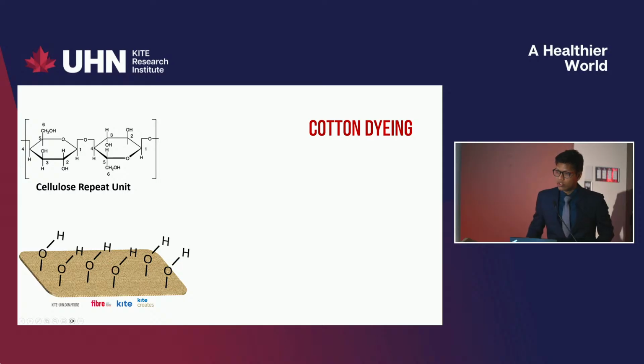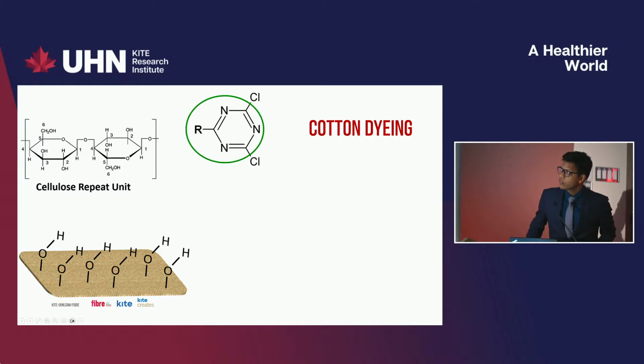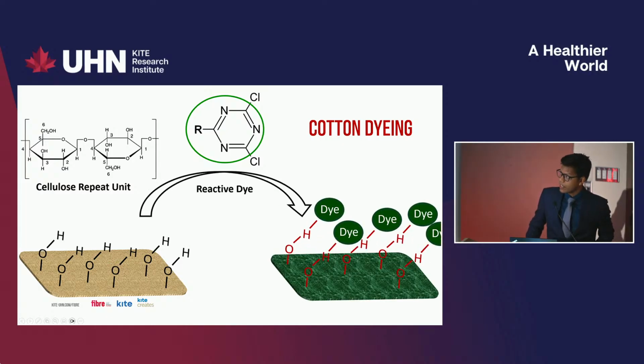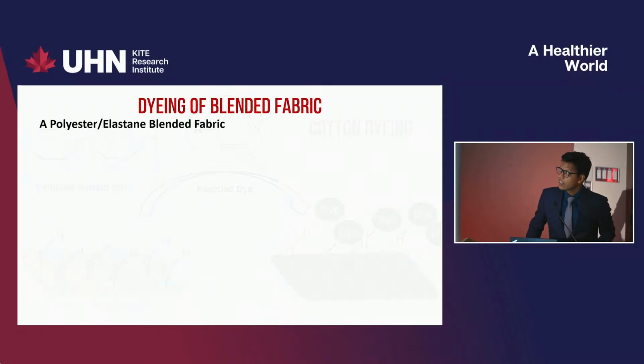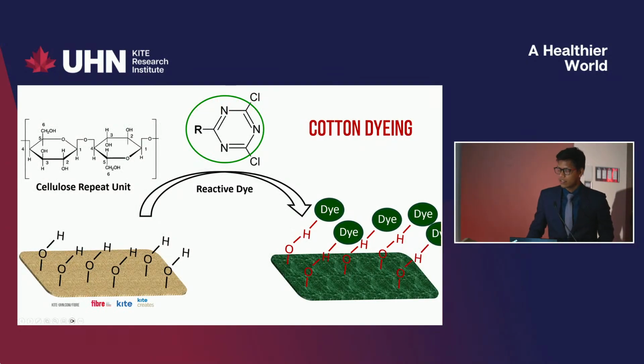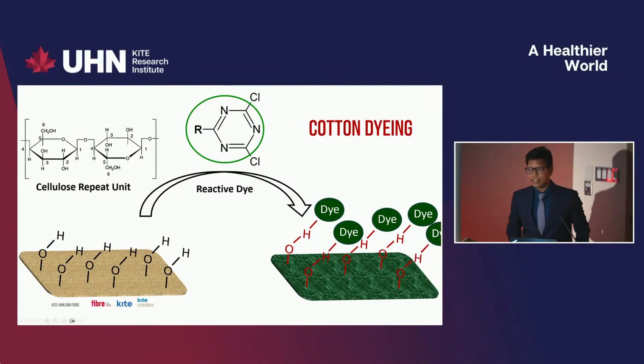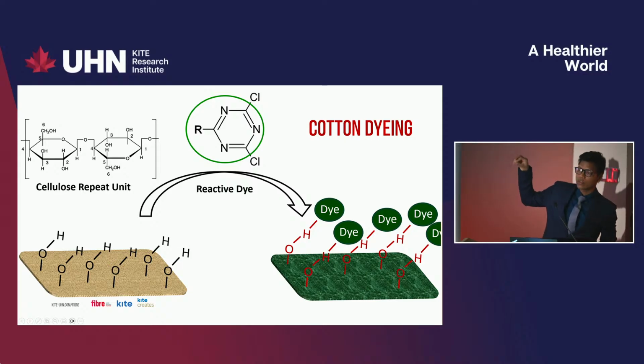So we include caustic soda, sodium hydroxide, in the dye solution. And for example, if you take one example of dye, this is an example of reactive dye. With the sodium hydroxide, we activate the hydroxyl group, and the hydroxyl group then reacts with the dye component, and it creates a byproduct, hydrochloric acid, and on the other hand, the dye gets fixed with the fiber.